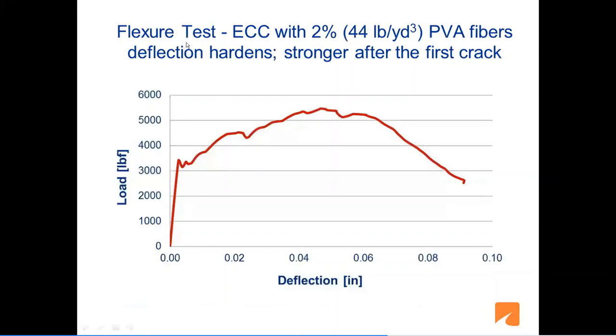Here is a result of a flexure test. ECC with 2% fibers, one of the original graphs we have done with 44 pounds per cubic yard, and PVA fibers were used in this. One interesting thing, as you look at this load versus deflection curve from the ASTM C1609 test, it shows that after the first crack, the material gets stronger with more deflection. And the reason is the fibers start acting, helping you.